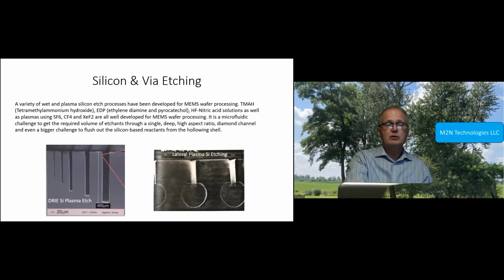Okay, next comes the micromachining part. You've got to both micromachine through that diamond shell, and then etch away the interior silicon. On the right are some old SEMs of some processes I developed years ago, where we do a high aspect ratio etching followed by an isotropic silicon etch in the underlying silicon structure. So it's kind of akin to that.